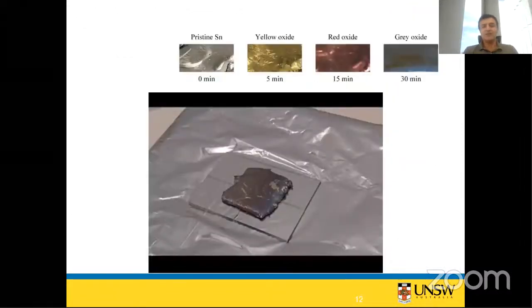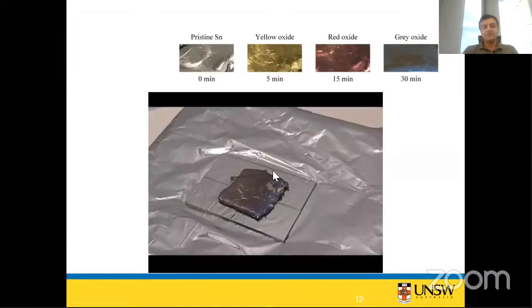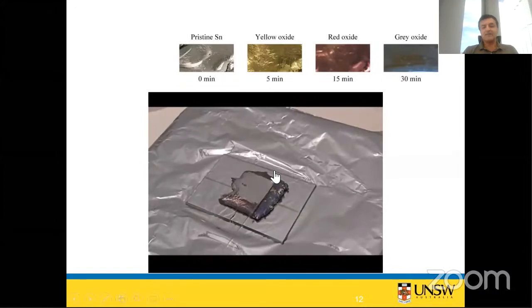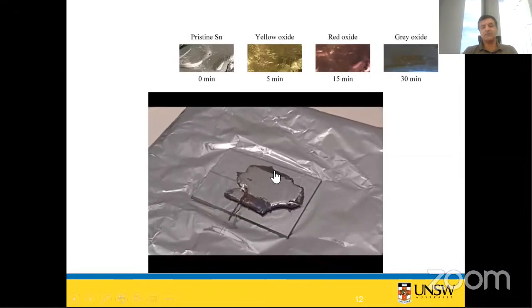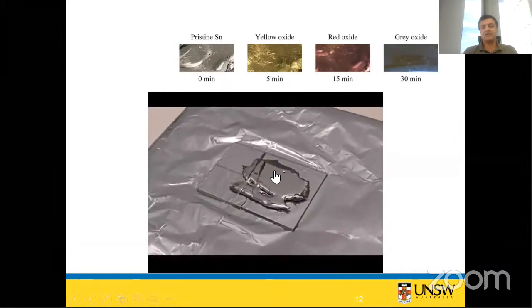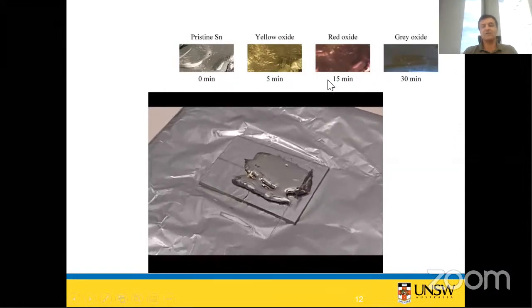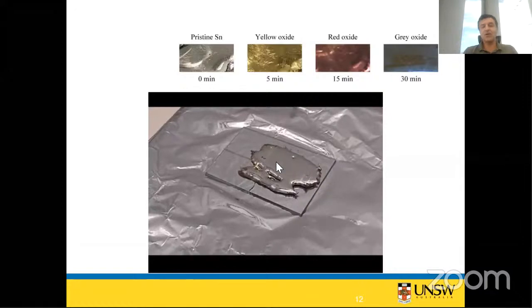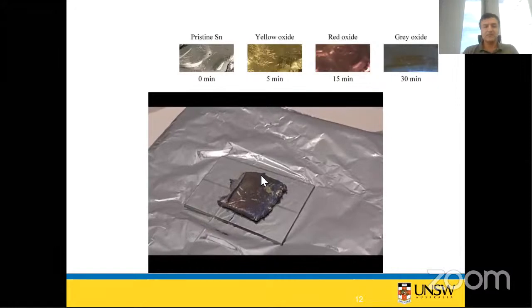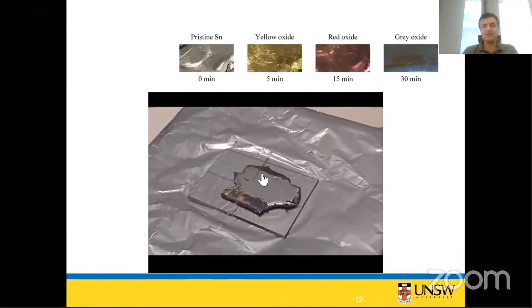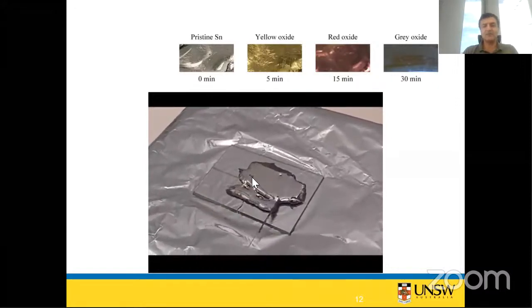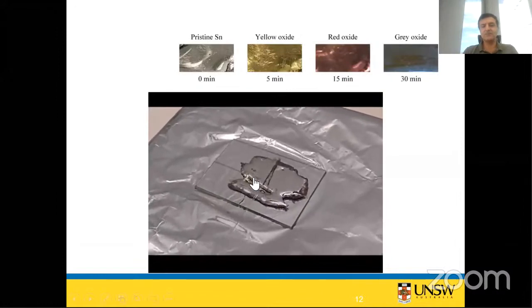So this is a liquid metal example. It's tin, and it's not self-limiting. In ambient, at 21% oxygen, it becomes thicker and thicker. As you see, you can take a piece of glass, and the 2D material on the surface sticks to the glass as the oxide of tin, tin oxide. So it becomes thicker and thicker and thicker. The color changes. The moment you harvest it, you get the second layer. As you see, the moment you harvest it, this area becomes yellow because it produces a very thin layer of tin oxide again. Yeah?